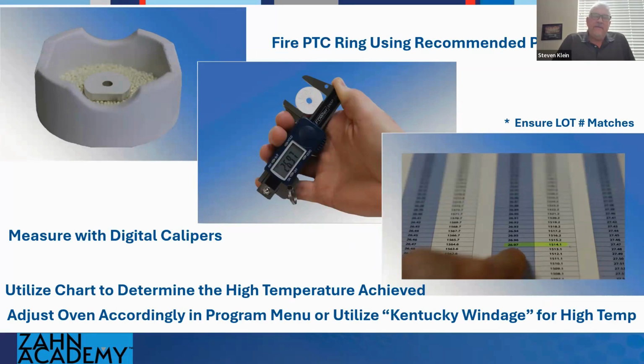So how do you do that? Of course, a firing tray, and there's a program that each one of these manufacturers recommend for their rings. I like to use the Orton Ceramics. There's my personal favorites, but you can try any of them and see which ones you like the best. The one I like to use is called the Temp Tab 700, and that's designed for a high temperature of 1500. So you set the program to do 10 degrees per minute up to 1500, hold for 2 hours, and then down at 10 degrees per minute.